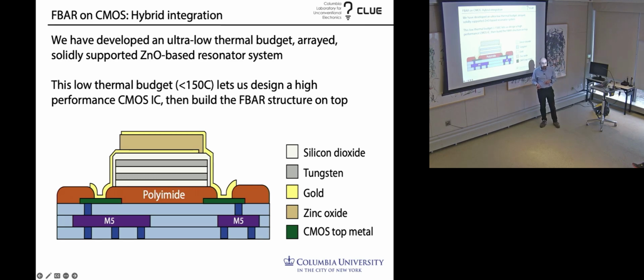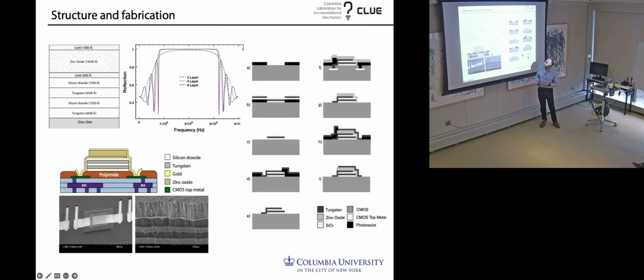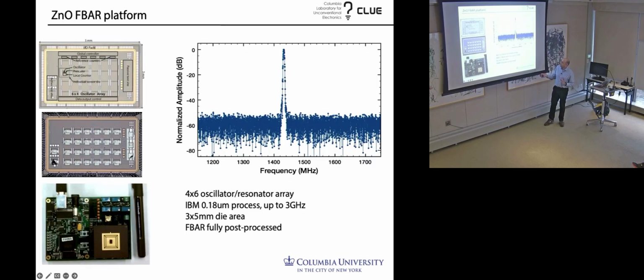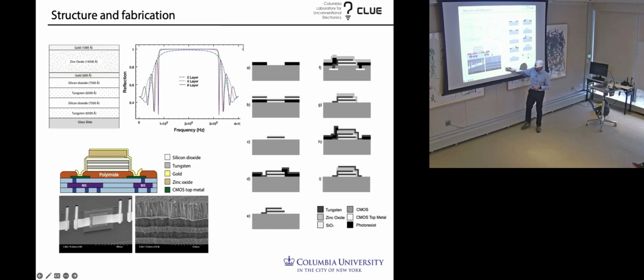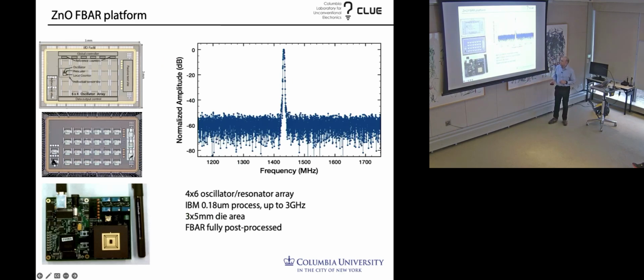Where in a quartz crystal monitor you might operate in the tens of megahertz, we're able to operate at 2.5 gigahertz, which really pushes up the sensitivity. Lots of processing and lots of cool things. I mean, the most important thing is that we do not need high temperature in order to get this nice crystalline texture, which is great, and there's some tricks to doing that.